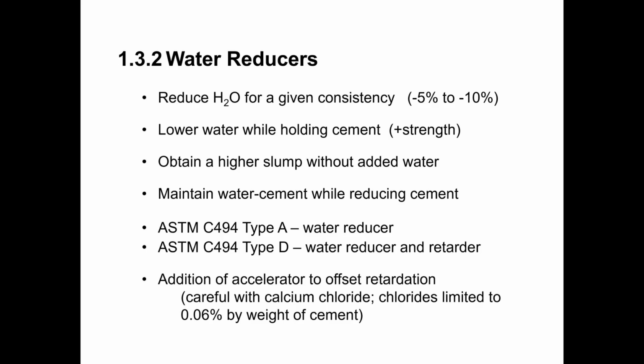The state of the technology of admixtures is to the point where most admixture suppliers can produce very effective accelerators that do not incorporate calcium chloride. So this is not as big of a concern as it was in decades gone by, but it is still a good question to ask your admixture supplier just to make sure that the accelerator that you're using is a non-chloride accelerator. We'll talk a little bit more about chlorides in cement as we review additional chapters as well.